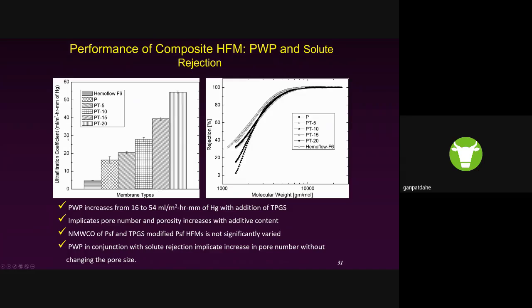This is the permeability of the hollow fiber membrane. This is water permeability. As you can see, the water permeability increases with increasing TPGS content. This is quite obvious, as we have more TPGS in the polymer solution, it diffuses out from the matrix and creates more porosity in the polymer, and that's why you can see more